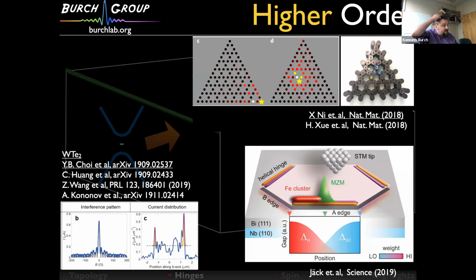I think some very nice work, which came out actually after ours, but was in tungsten telluride, which was also one of the early predicted systems to have hinges, where people used basically Josephson junctions and showed that when they did this Fraunhofer spectroscopy, they could see that there was sort of current being carried along these one-dimensional hinge modes. It only showed up on the right crystal faces.